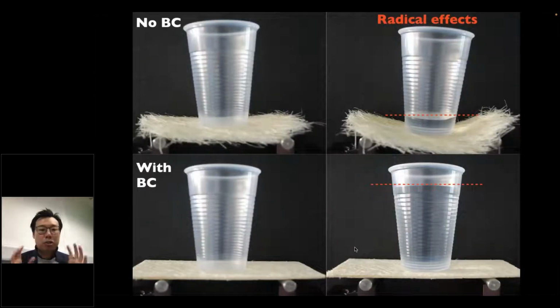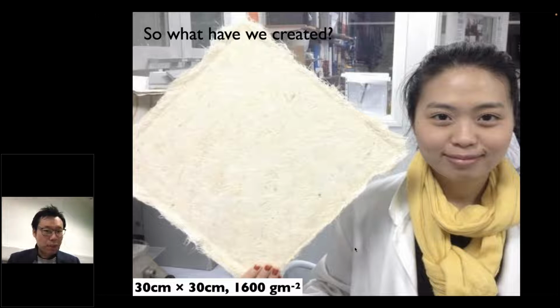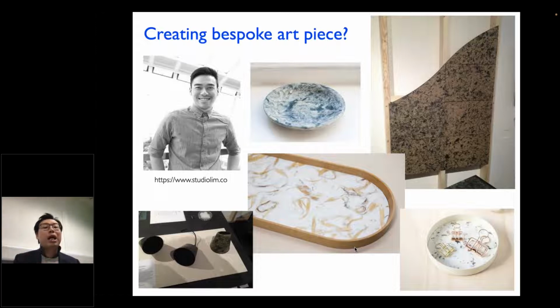How rigid are we talking about? So the top two pictures are a fiber network without cellulose. The bottom two have bacterial cellulose added to it. You can fill in a glass of water. It can sustain the weight of a cup of water, doesn't deform at all, whereas the ones without cellulose deform quite easily. You can make it as big as possible because this is a simple paper making process. So that is actually a rather big piece of material that the student there was holding at the bottom. It doesn't flex. And you can create art pieces out of it, to replace your fiber boards that typically contain about 10% formaldehyde glue, with just this nanocellulose.